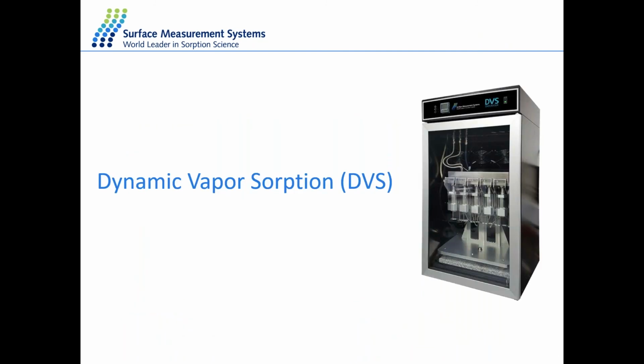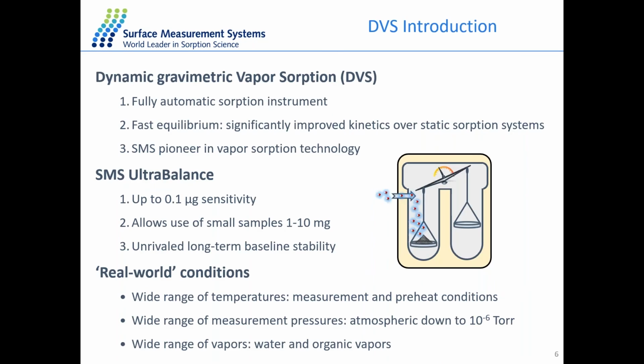So first we will focus on the dynamic vapor sorption technique. Just a brief introduction. DVS is a gravimetric method where we measure the mass change of the sample at different concentrations of moisture or organic vapors. It is based on a very accurate balance in the system with a resolution of 0.1 microgram. And this allows us to use a very small amount of sample for the analysis, typically just around 10 milligrams, as long as the sample has a good water uptake.